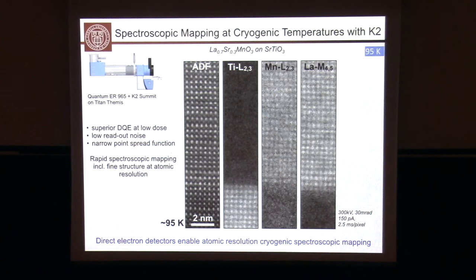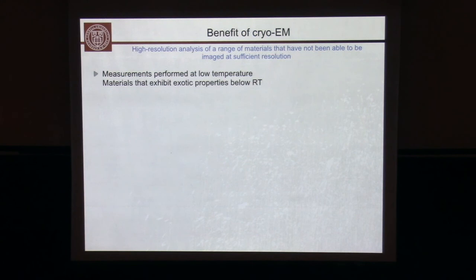So these are direct electron detectors that have been traditionally used in cryo-electron microscopy for biology. We have now enabled this for spectroscopy, and that has allowed us to record spectroscopic maps at low temperature, and will allow us also to look at charge order effects as you go through phase transitions. Okay, so the first example was exotic or low temperature phases.